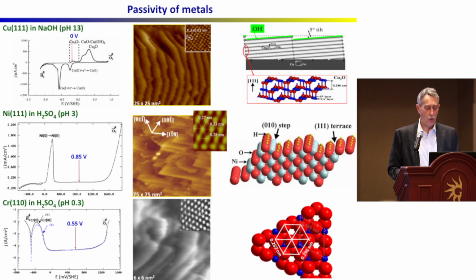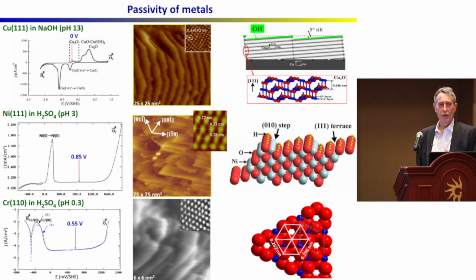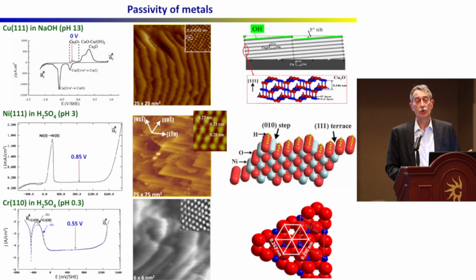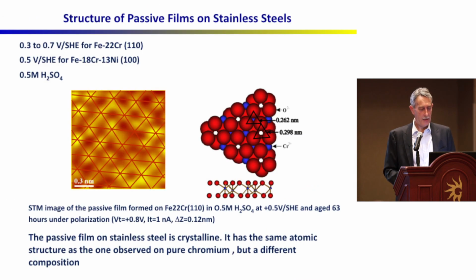And similarly with chromium, you get the most stable surface, which is the basal plane of alpha Cr2O3, where you have the highest coordination of atoms. And chromium is a good model for stainless steel. So of course, on the stainless steel, there will be iron in the oxide. But then we did measurements on stainless steel, and this is what we get.